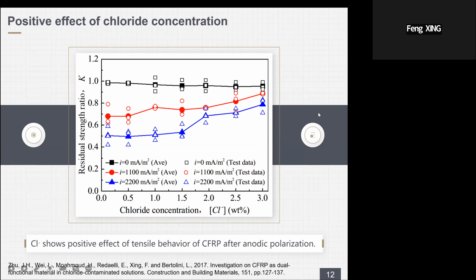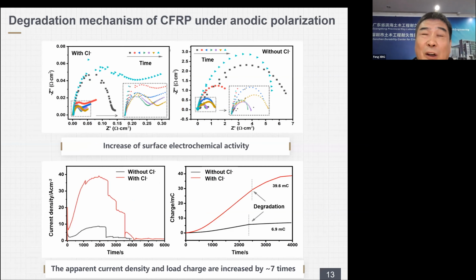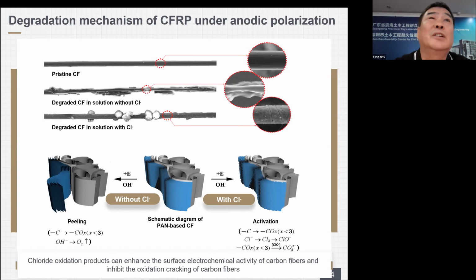To further study the mechanism, here we investigate the effect of chloride on the anodic behavior of single carbon fiber. From the EIS, we can observe the carbon fiber has a smaller surface electron transfer resistance in the solution containing chloride ions, which shows the ion diffusion control process, indicating that chloride ions can generally improve the surface electrochemical activity of carbon fiber. The current-time curves show that the carbon fiber has a higher current response in the chloride solution, and its apparent current density and charge load are greatly improved, thus extending its service life as an anode material.